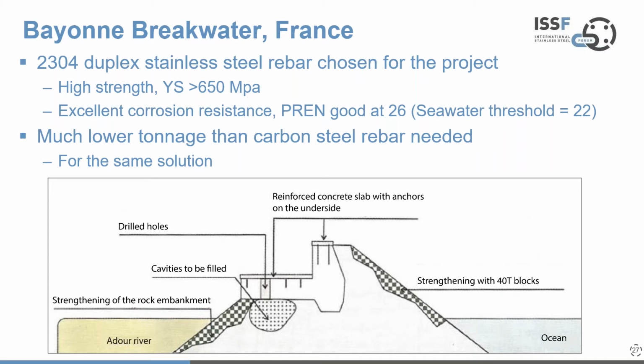And for the repair, 2304 duplex stainless steel reinforcing bar was chosen for the project, really for 2 main reasons: a high strength, so a yield strength of greater than 650 megapascals, and excellent corrosion resistance. The pitting resistance equivalent number was above the seawater threshold, and that's important because in chloride rich environments, pitting resistance is the main form of corrosion, the main corrosion mechanism.